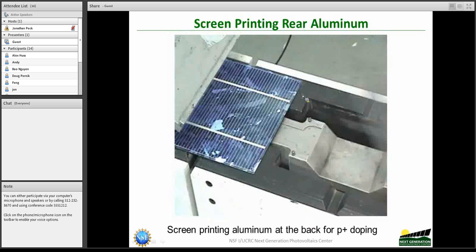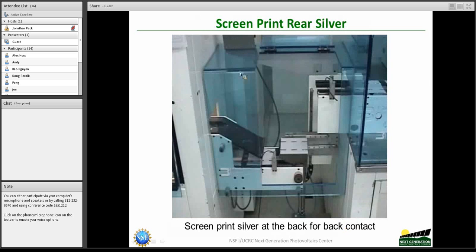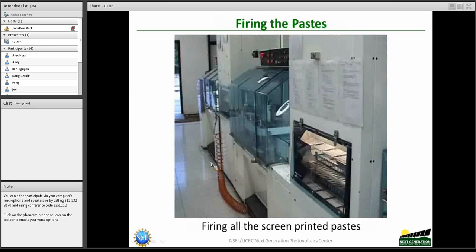The next is screen printing aluminum at the back. The aluminum is the P-type dopant, and screen printing aluminum at the back makes a P+ doping. And subsequently, screen printing silver at the back, which is the back contact. And the last step in making the cell involves firing all these pastes together: the paste for the front contact, the aluminum at the back for P+ doping, and then the screen printed silver. This is what is involved in making the cell for silicon material.